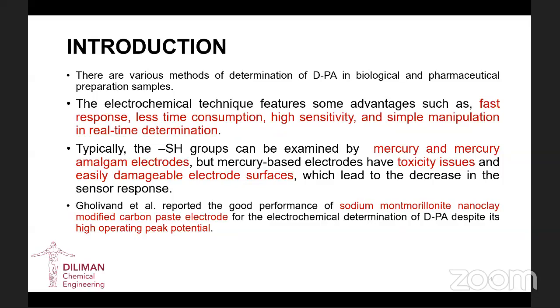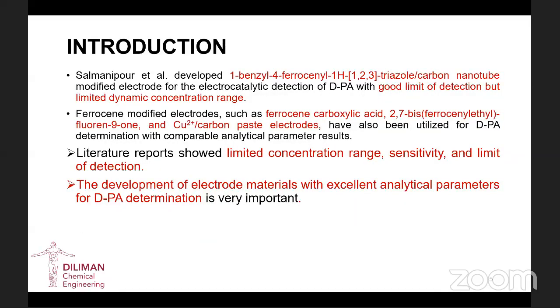And there was a study before by Gholivand et al., which reported a good performance of sodium montmorillonite nanoclay modified carbon paste electrode for the electrochemical determination of penicillamine, but it has high operating peak potential or voltage. So other studies show the development of 1-benzyl-4-ferrocenyl-1H-1,2,3-triazole carbon nanotube modified electrode for the electrocatalytic detection of DPA with good limit of detection but limited dynamic concentration range. Also, ferrocene modified electrodes has also been utilized for DPA determination with comparable analytical parameter results. However, these reports show limited concentration range for the detection, and then lower sensitivities and lower limits of detection.